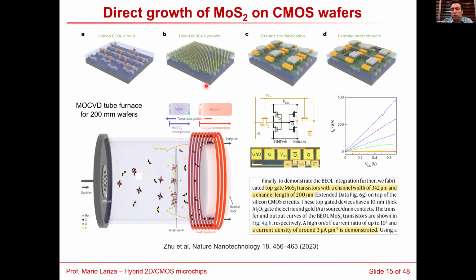There is another different approach, for those who don't believe in transfers, that has been recently reported by a group at MIT, in which basically they design a silicon wafer, and then they grow the 2D material directly on it. But as I mentioned, this cannot be done at high temperatures. So what they do is they have a CVD system with a zone that is at 250 degrees, which is a temperature that the transistors can survive, and another zone at 550. And therefore, they manage to make the reaction in the high temperature zone and deposit the material on the wafer that is in the lower temperature zone.